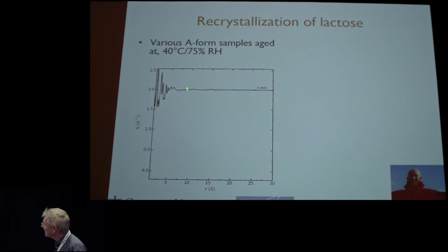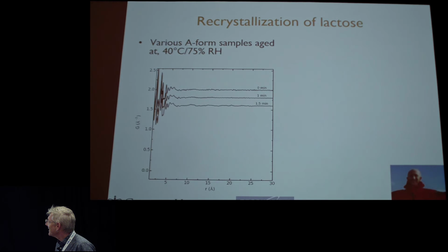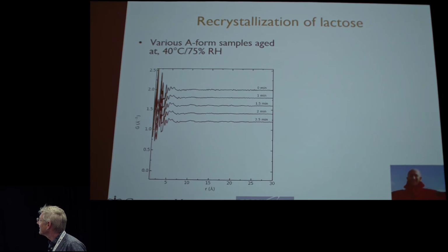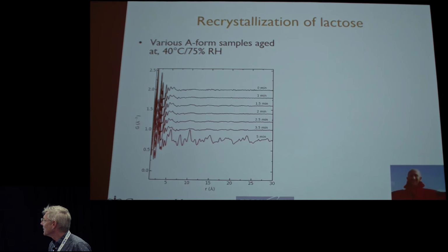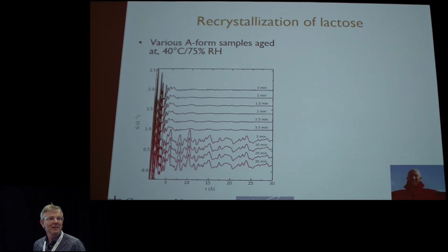Anyway, what we wanted to do was study the recrystallization. So this is amorphous lactose. This is the lactose molecule PDF, and the intermolecular signal is kind of flat. And then this is undergoing an enhanced aging. So after 1 minute under these conditions, it looks like this, 1.5 minutes. And you can see a little signal starting to pop up here. So it's starting to recrystallize, 2 minutes, 2.5 minutes, 3.5 minutes, the signal's getting more robust. 5 minutes, bam, it's gone. And then you leave it for longer, it stays crystallized, so it's irreversible.